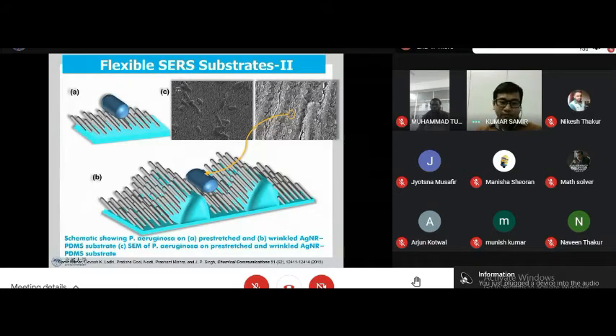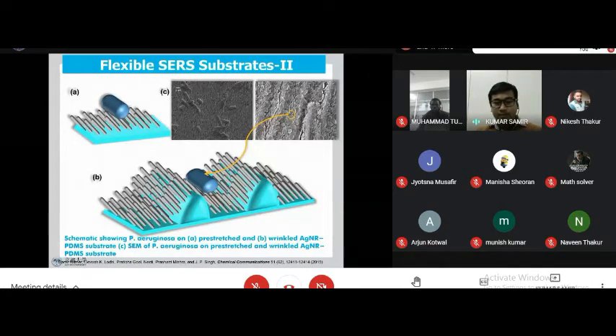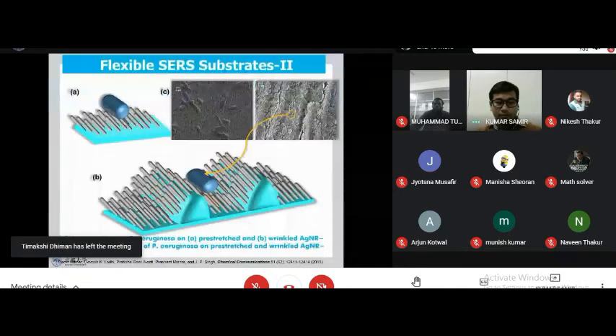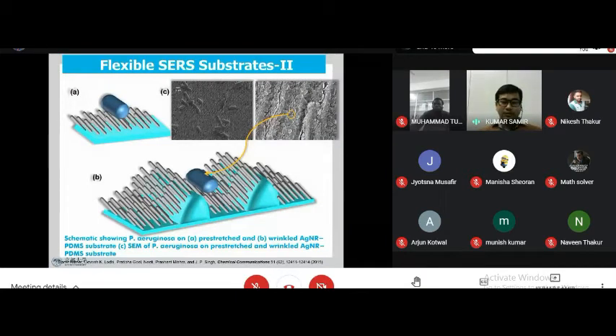But when we release the stress, the bacteria is captured within this cage of wrinkles, from the two sides also. Now the number of hot spots that are touching the bacteria increases, and that may be the reason for the increase in the SERS signal. So we enhance the number of hotspots in the third dimension also using this technique.